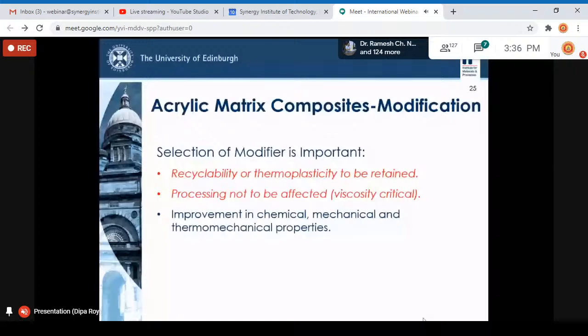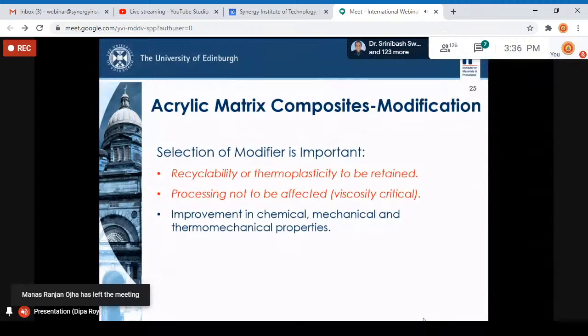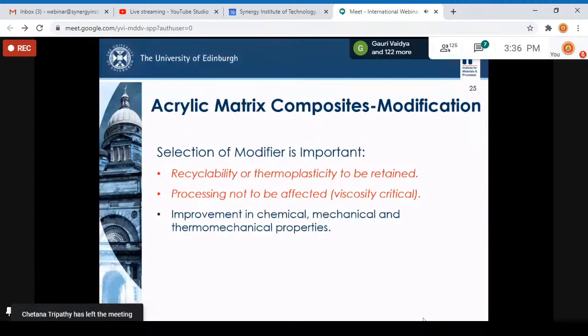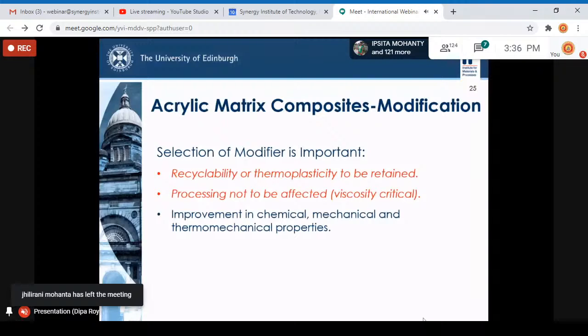And we had to select some modifier polymer, because the main purpose of the modification is enhancement of the property, but at the same time, you have to keep in mind that the recyclability should not be lost. We have to retain the recyclability, which is critical for future sustainable materials. And at the same time, we should not increase the viscosity of the resin significantly so that the manufacturing is hampered. Because here, the room temperature liquid resin infusion is critical. It's very important. If we increase the viscosity by some modification, then that is not going to help the infusion process. So there is a limitation on how much we can modify. So these two are the most critical considerations when we thought about this modification.